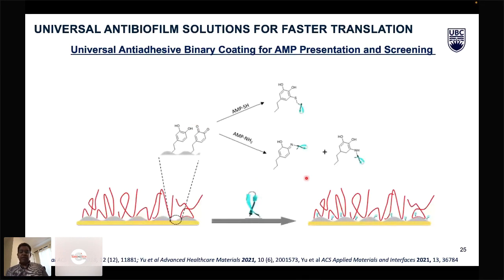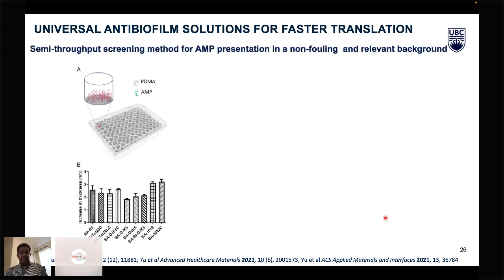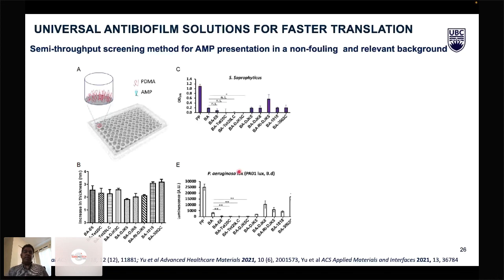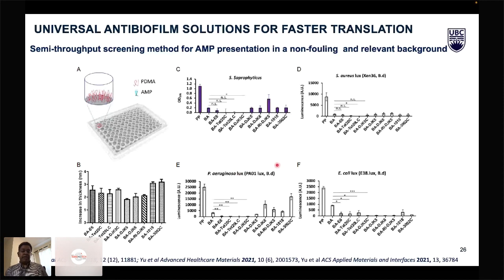So here we further modified it, and developed the chemistry to attach antimicrobial peptides on the surface, which is still able to prevent bacterial adhesion, as well as kill the bacteria. We utilized our 96 format and screened a number of peptides and a number of bacteria, and we identified a set of peptides which, in combination with the anti-fouling surface, is remarkable in preventing